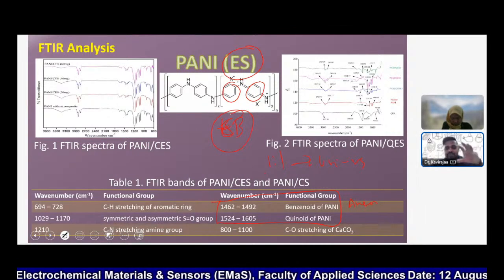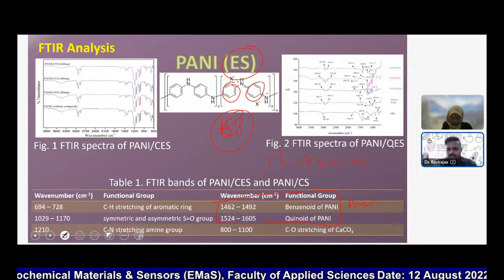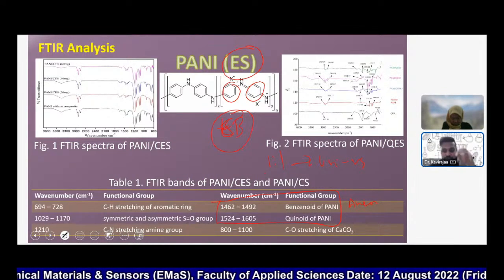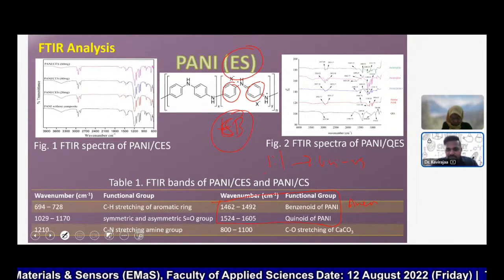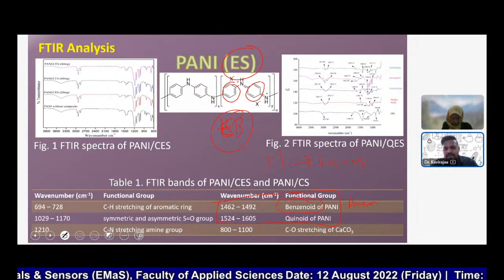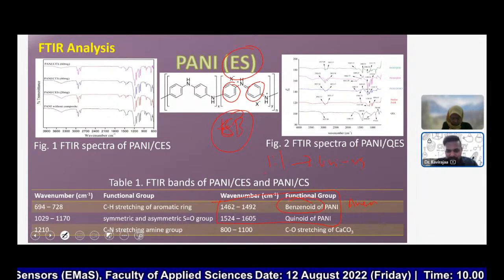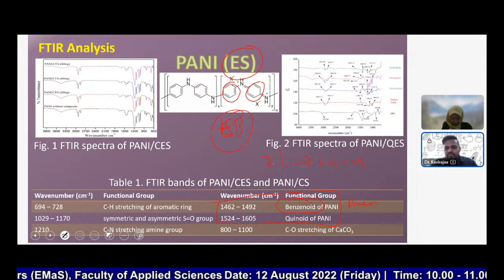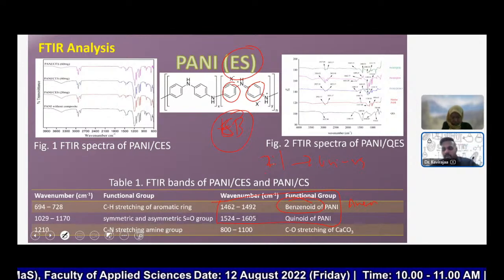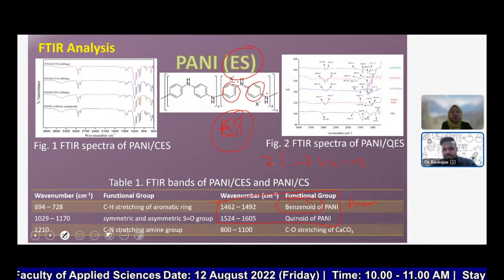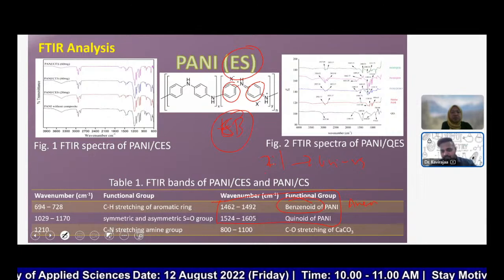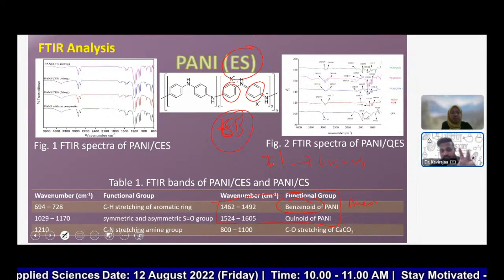Okay, because these two structures will have an equal amount of benzenoid and quinoid. But if we look at the leucoemeraldine, then we will get a higher ratio of benzenoid. So maybe just simply write numbers over here, maybe 2 to 1. The benzenoid will be more for the leucoemeraldine. So this is the way that we can prove a little bit on the formation of whether we got this